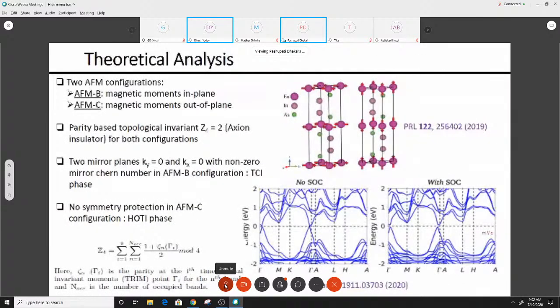So below the AFM transition, this crystal can have two almost energy-degenerate configurations. One is AFM-B, in which the magnetic moments are in plane, and the other is AFM-C, in which the magnetic moments are out of the plane. We also performed first-principles bulk band calculations, which we can see here.